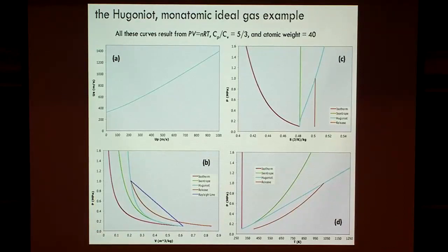So the steady behavior is a constant particle velocity? Or constant particle velocity, constant pressure, constant density, constant temperature. A well-defined thermodynamic state. But all you're measuring is the particle velocity. Is that correct? We measure it in different ways. In order to get a full characterization, we usually have to measure both the shock velocity and the particle velocity, or the shock velocity and the impact velocity of the projectile in a gun-type experiment, or have some sort of reference that tells us that other variable.